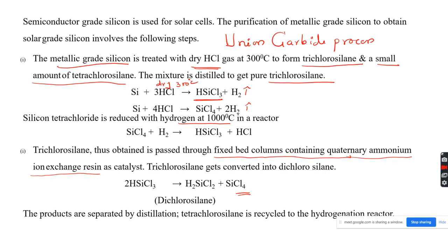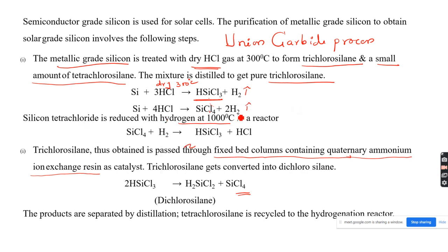Now, semiconductor grade silicon used in solar energy is usually manufactured by the Union Carbide process. That is nothing but a purification of metallurgical grade silicon into solar grade silicon. The metallurgical grade silicon, if you treat it with dry HCl gas at 300 degrees Celsius, forms trichlorosilane and tetrachlorosilane. The mixture is separated by distillation. Then tetrachlorosilane is again converted into trichlorosilane, reduced with hydrogen at 1000 degrees Celsius. The trichlorosilane thus obtained is passed through a fixed bed column containing quaternary ammonium ion exchange resin. As a result, trichlorosilane is converted into dichlorosilane.